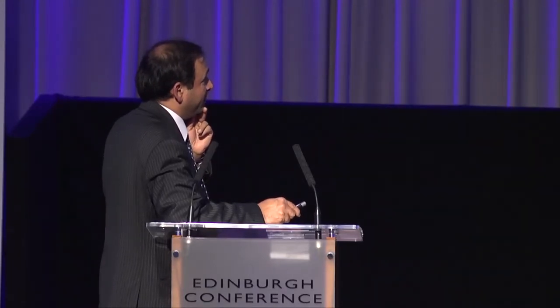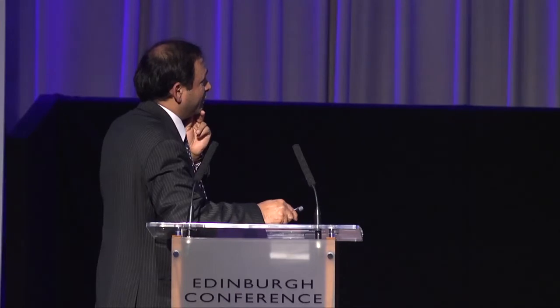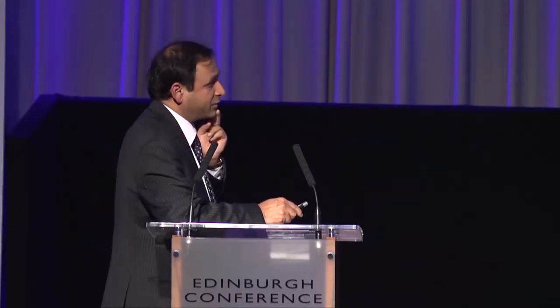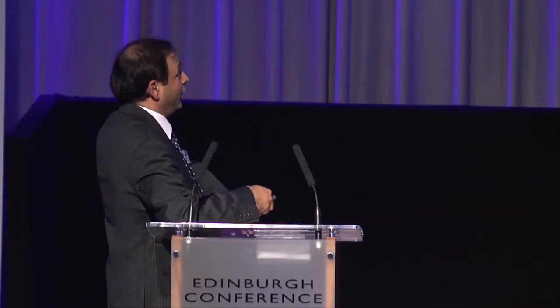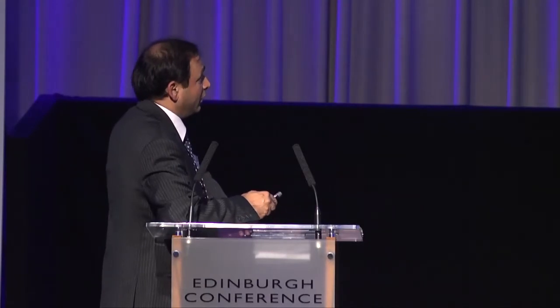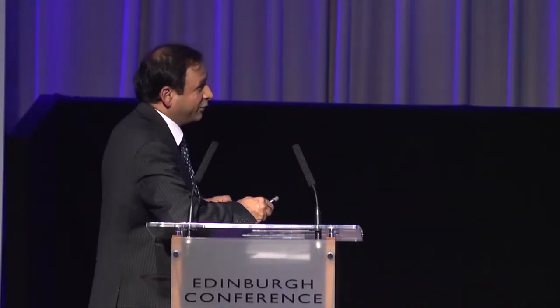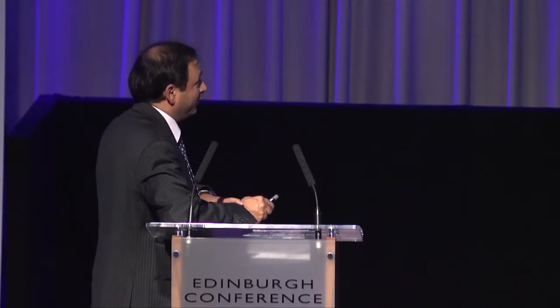This was obviously made by me at Imperial College in 2003, where we achieved 5.3% on plastic foils using an all low temperature processing route. So the highest temperature we used in making these cells was 100 degrees centigrade and below. So these technologies, along with now organic PV, which is another topic of interest amongst PV people.